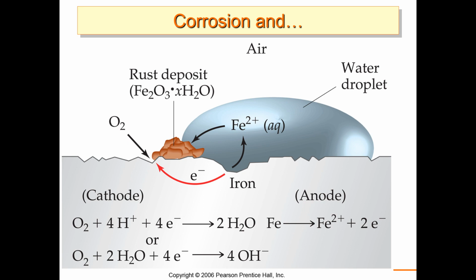A lot of times it's in valves. They get in the threads of the valves and they set up a little bacterial colony and they use the metal potential to power the cell, and they produce acid, and that acid will eat right through the metal. So it's amazing. So that's part of corrosion prevention: not just controlling chloride, but also controlling bacteria.